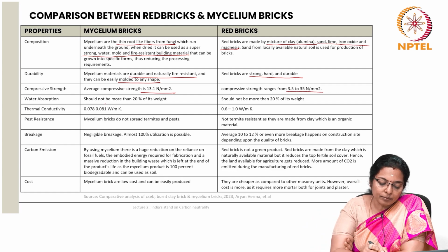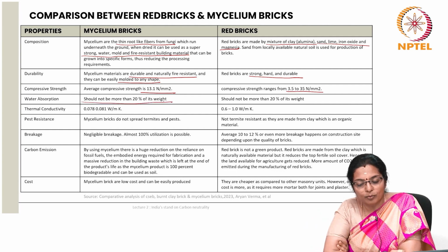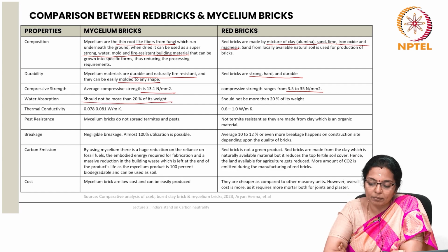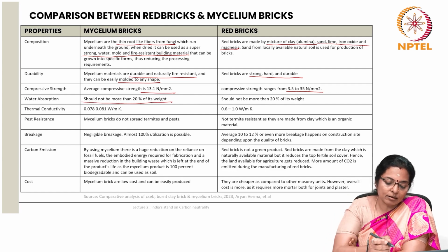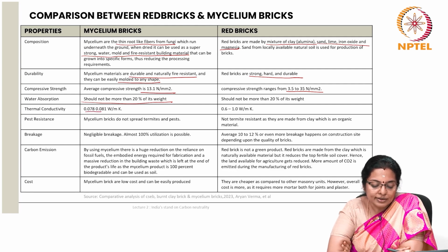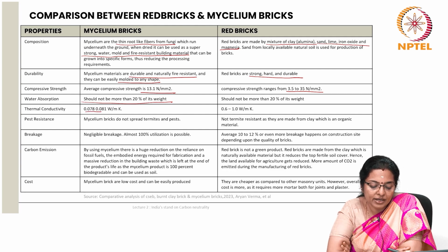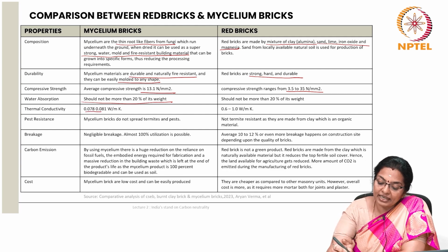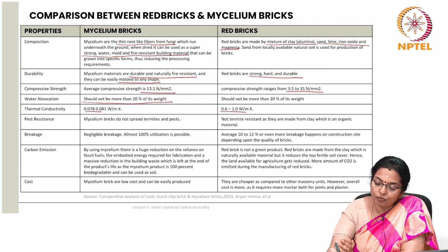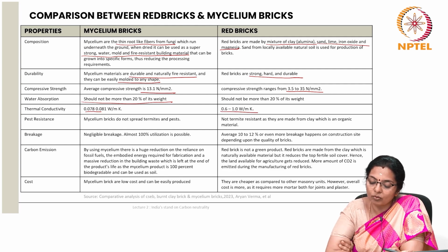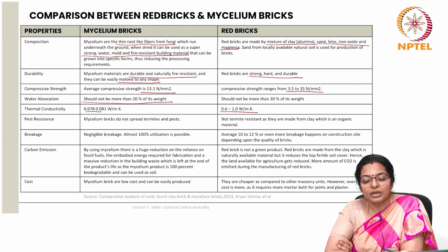Water absorption should not be more than 20% of its weight for mycelium bricks and red bricks, and it is achievable. Look at its thermal conductivity. Thermal conductivity is only 0.078 to 0.081 watts per meter Kelvin. But red bricks have a conductivity of 0.6 to 1 watts per meter Kelvin.